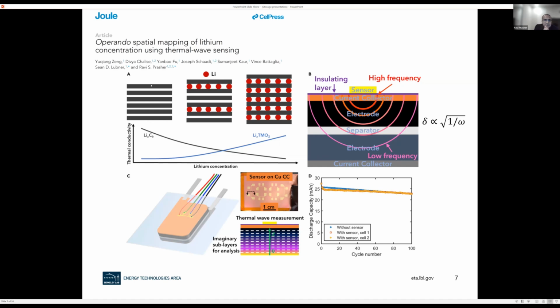Because what happens is, when this is graphite, the parallel planes, lithium comes in, right? It changes the lattice constant. That means it changes the phononic behavior, which is responsible for heat conduction, and that changes the thermal conductivity. So that is the phenomenon that made us start thinking, okay, that means if I can measure the change in thermal conductivity, I can back calculate